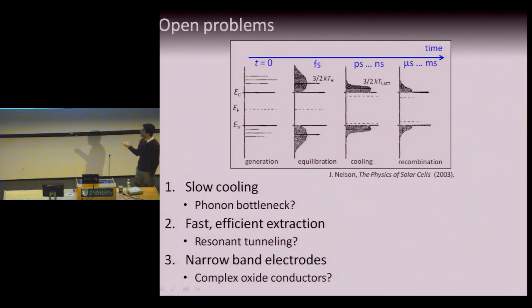The second problem is that of fast, efficient extraction. So if you want to slow down one process, presumably it's because you want to speed up another process so that they can occur on roughly the same time scale. This is the problem that I've been thinking most about and is the problem that motivates the material science work that I'm going to present later on in this hour. I propose in particular to use resonant quantum mechanical tunneling as a way of extracting charges quickly and efficiently, although I don't want to dwell so much on this process as tell you that there are known pathways, not yet implemented for good material science reasons, to try to get this done.